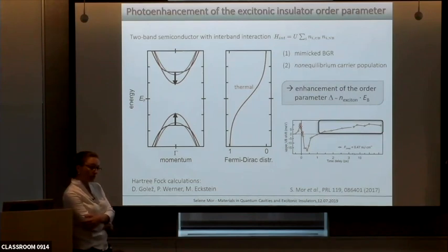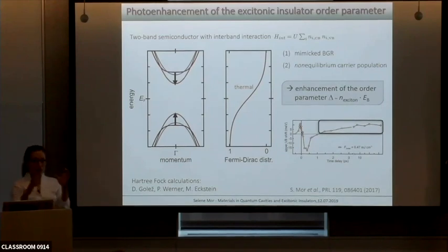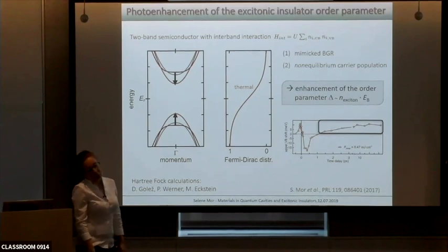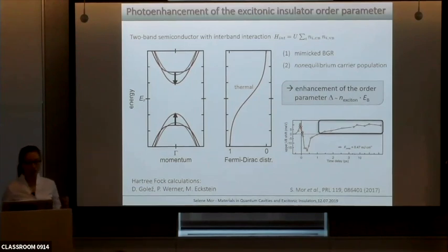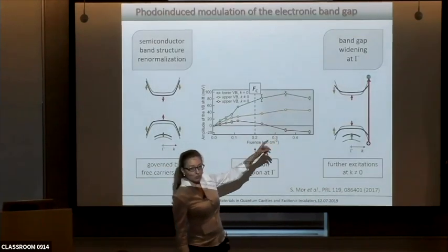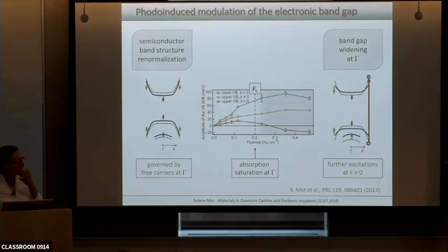So I could take this half a picosecond as the condensation time scale, in the picture where you open the gap because you increase the condensate density. Yes, the idea is that you have to consider this kind of population to account for the increase of the condensate density, and those excitons have to find the gamma point first, if the gamma point is the minimum.